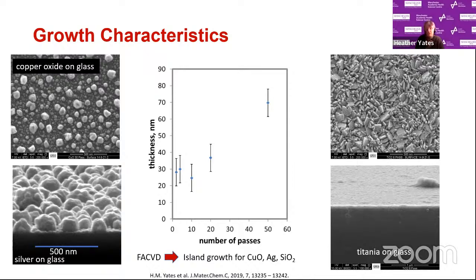On the right, I've got the material I'm intending to mix it with, which is titania. You can see that is much smoother. This is done by thermal CVD, and it's a much more compact, smooth film.